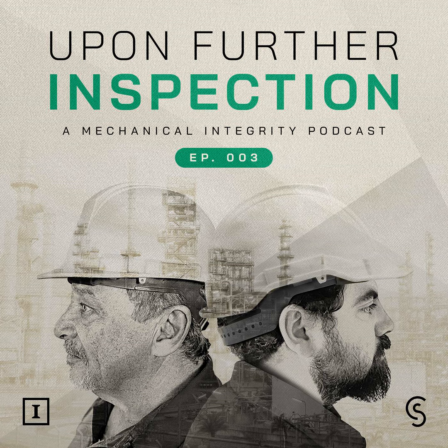was a corrosion engineer with Shell at the Martinez refinery, did that was so cool, because he had an effluent heat exchanger that was riddled with HIC-SOHIC. And when I was at DNV, he had us do a 100% AUT scan of the whole vessel, the heads, the walls. And then he had the color graphic images. So what he'd do is he'd take the drawing and lay the plate out flat, like just change it from being a cylinder to a flat plate. Right. And then he could look at the P-scan data for 100% of the vessel.